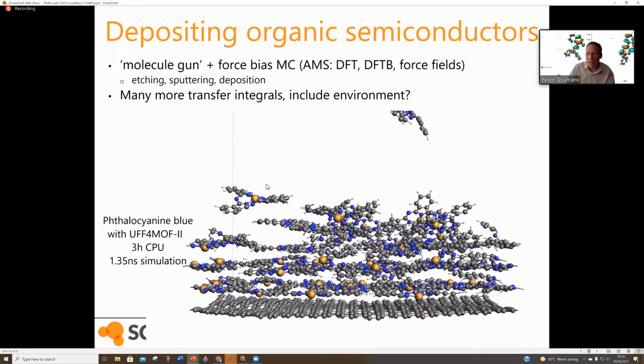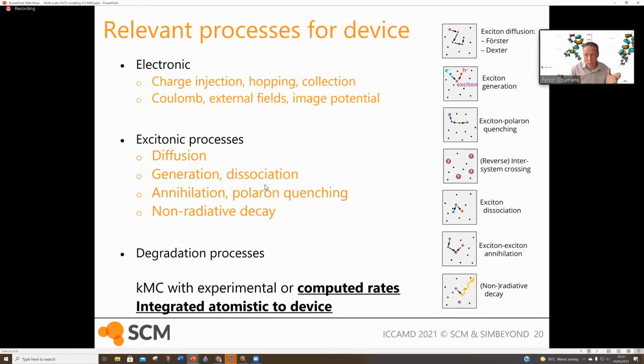So the idea is then, okay, you build your OLED stack. So you have your hole transport layer, your electron transport layer, your injection layers, and your emission layer. And then for each one of these, you define your molecules, you do the deposition, as we just saw, and then calculate the relevant properties for that layer. Or if we cannot calculate them for some reason, we can input experimental parameters as well, or guess them based on perhaps database values, and then do the full kinetic Monte Carlo calculation on the device level.